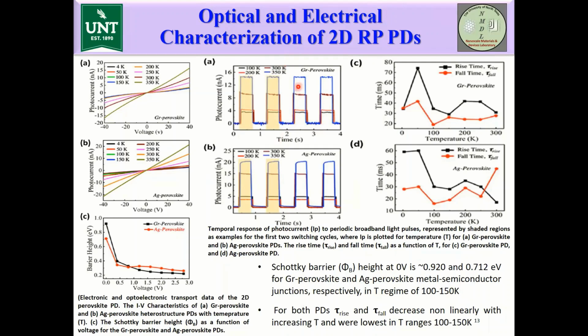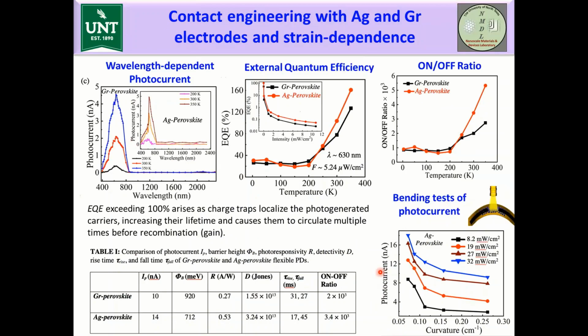Now these two are showing the photocurrent response with time for graphene perovskite and silver perovskite photodetectors. And these two figures are showing the rise time and fall time of graphene and silver perovskite photodetectors with temperature. Here we have studied the wavelength-dependent photocurrent for both these perovskites in different temperature regions.